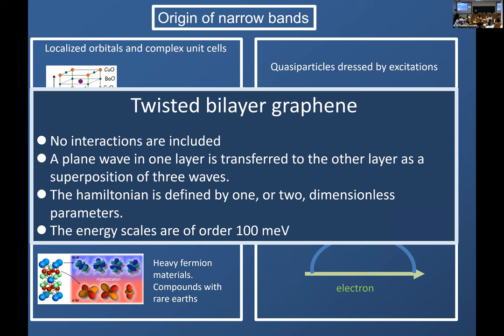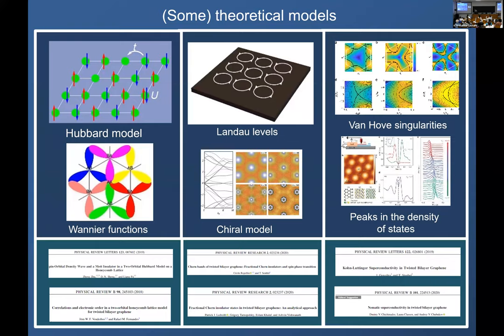This is a non-interacting model. All the parameters you plug in are in the scale of 100 meV or larger—that's the interlayer tunneling and the intralayer hopping. At the end of the day, you get bands whose width can be a few meV. That's very unusual and has no counterpart in a typical strongly correlated system. Because of that, because of the complexity of the model—this is just a cartoon—we theorists have tried to analyze it from many points of view.